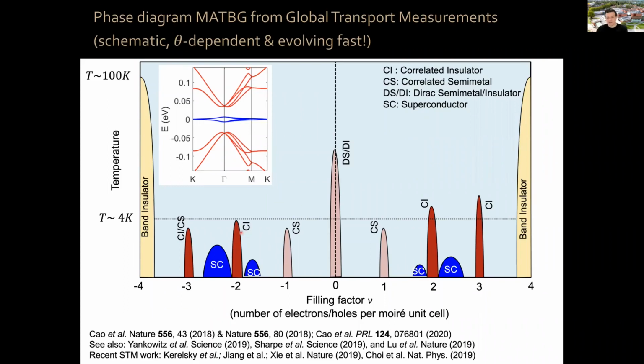Now, other than the insulating states or semi-metal states, what is also interesting is that you see in certain regions superconductivity. The most pronounced and robust superconducting dome is the one at 2 holes plus extra holes per Moiré unit cell. This is the biggest dome, typically. You also see quite frequently the one at 2 electrons plus extra electrons. And you see sometimes these other domes, and here and there have been some reports of some other domes in some of the regions of this phase diagram, okay? But these are the most robust, especially this one and this one.